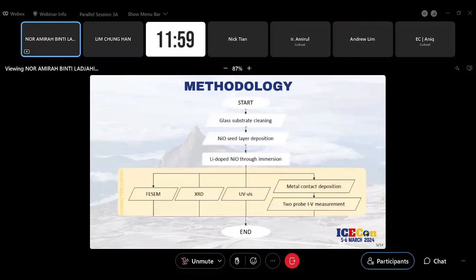So this work basically examine the lithium doped nickel oxide properties to be compared with the pure nickel oxide. To develop undoped nickel oxide and lithium nickel oxide sample, we started with the glass cleaning, because we deposited the sample on the glass substrate. We deposited nickel oxide solution through a sol gel spin coating method, which producing nickel oxide thin film. We continue the process through the immersion method. Then we continue with the characterization.